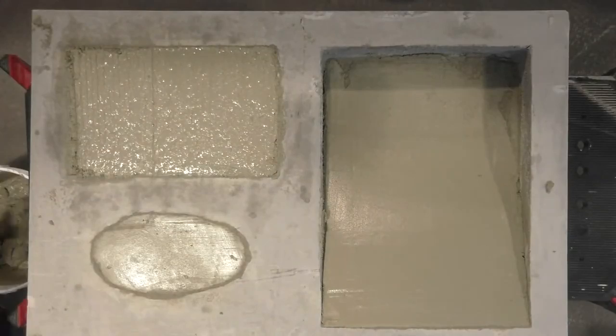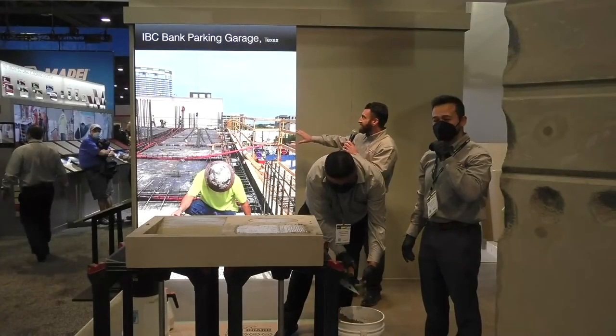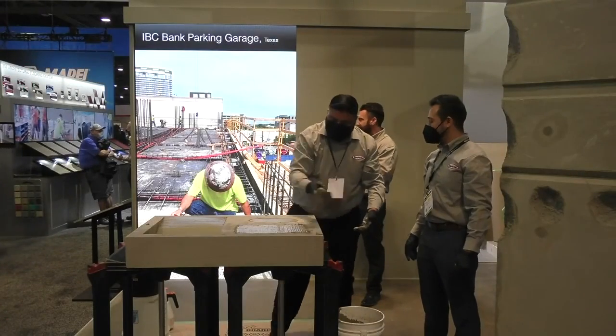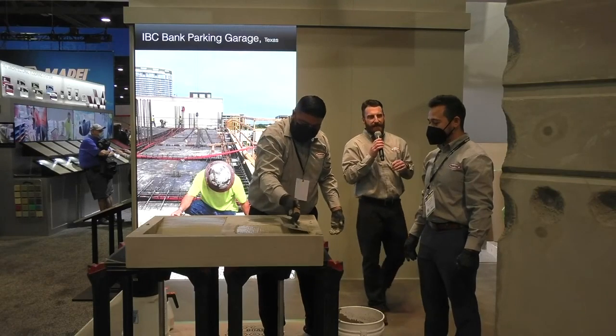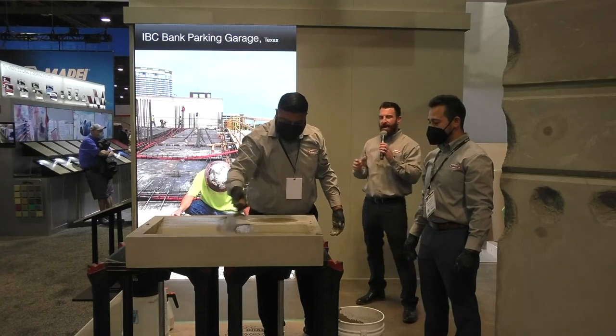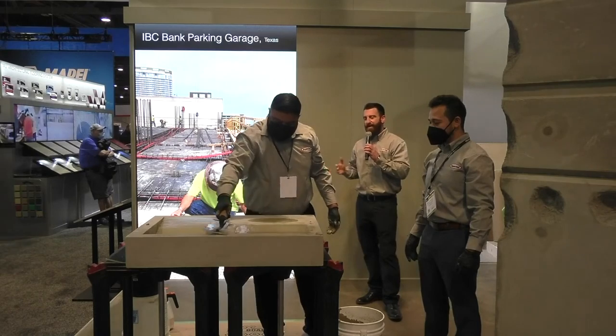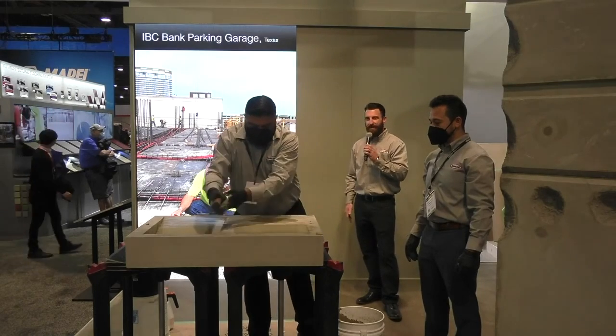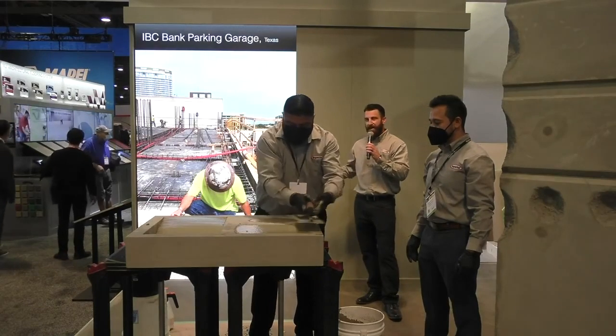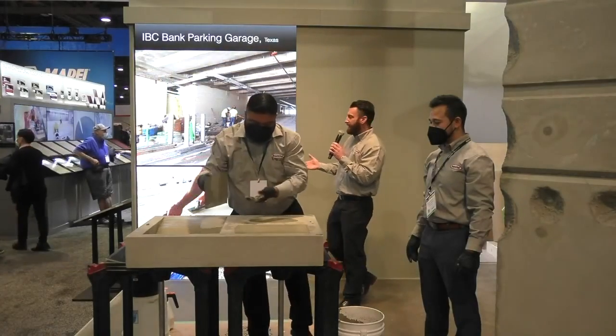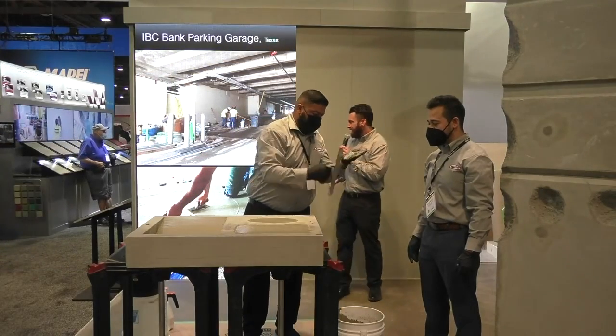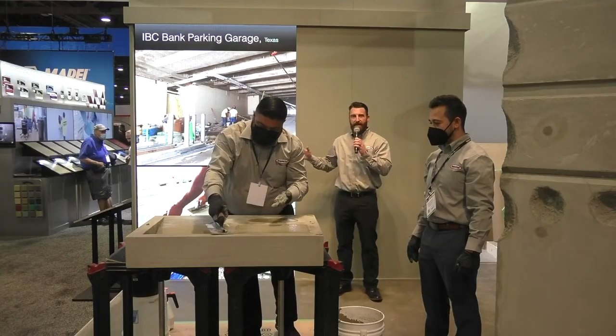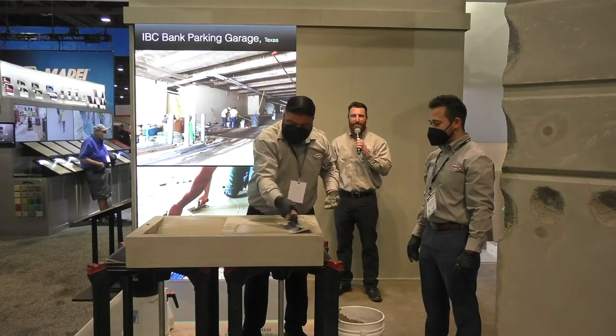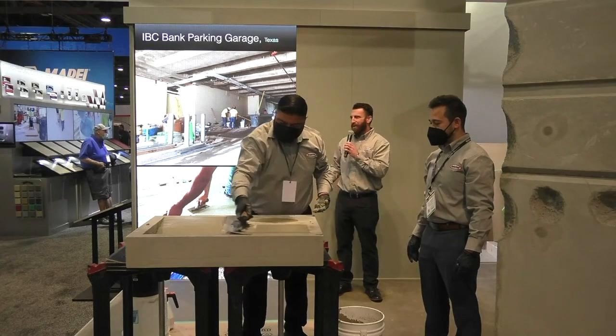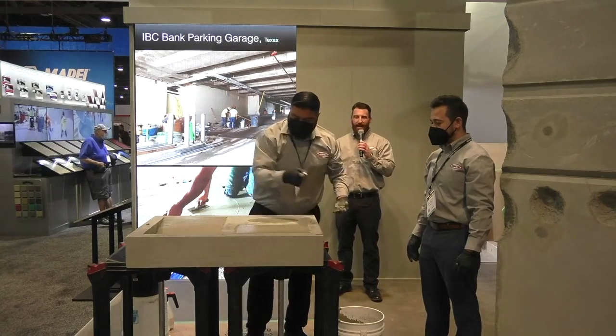So here's a few projects where we use some of these products. This IBC Bank parking garage in Texas. This one, they had a very poor broom finish, and so the car tires, when the surface was wet, would turn and be slipping on the broom finish. So they came back, they used the Cementol, placed it at a 1/2 inch thick, finished it with a sponge float and gave it a broom finish. And they were able to close down this parking structure overnight and open it up the next morning.